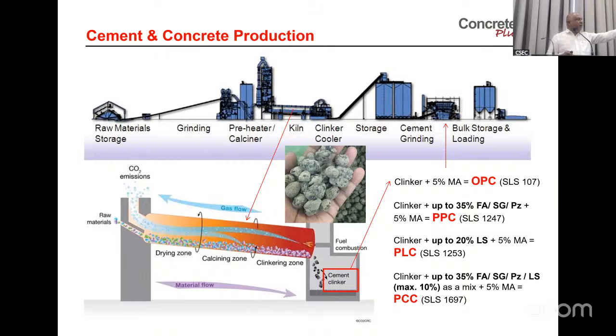OPC is only clinker with 5% minor additives, as I mentioned earlier. Then PPC is up to 35% fly ash, slag, or pozzolan. Limestone up to 20%. For composite cement, you can add up to 35% fly ash, slag, pozzolan, or limestone. There is a limitation on limestone; you can add only up to 20%. Because you are going as a mix, you can go maybe 20% fly ash, 15% slag, or like that. So these are available in the market.